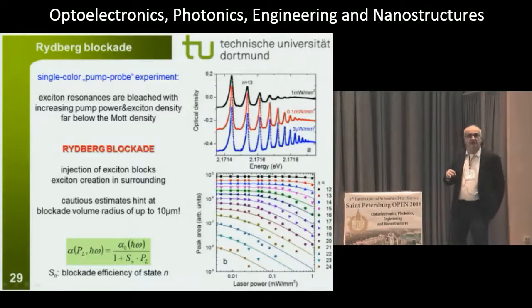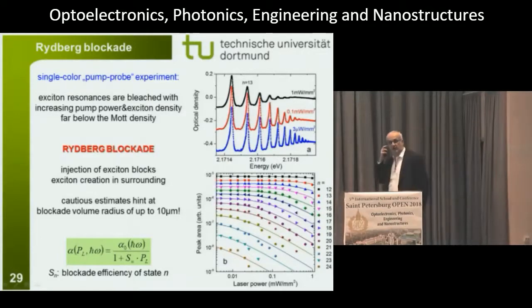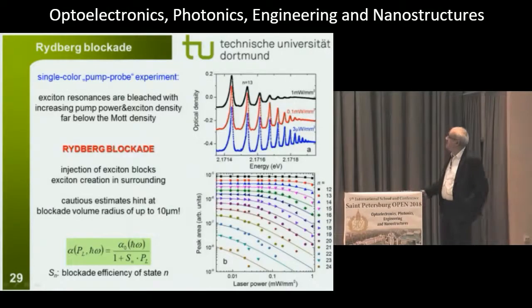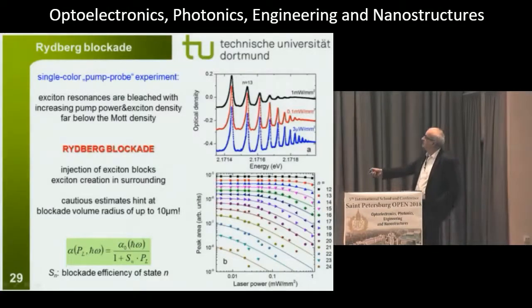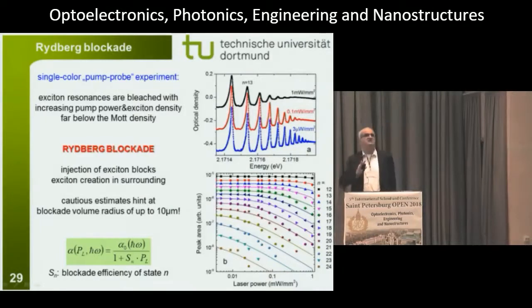What we did then, in a very first approximation, because we had no idea, actually nobody knows exactly how to describe exciton-exciton interactions. This is a terribly complicated problem, and we are just working on this. But just to get a first idea of what is going on, we fitted these data by this formula, where your absorption at a particular laser energy using a particular laser power is given by the absorption spectrum recorded if you would apply zero laser power.